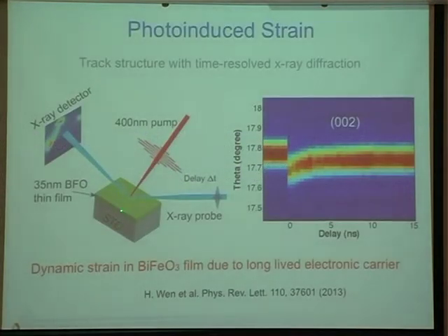So one is the idea of what you can do optically in a film with light. I'm showing you here an experiment where we're doing an X-ray diffraction measurement, time resolved, after we've pumped the material with laser light. And this was bismuth ferrite, which is a multiferroic material. And what we found was you can induce ultra-fast strains in these materials. In a film, this is very interesting because the film can't move sideways because it's clamped to that substrate. So it can only move in the out-of-plane direction.